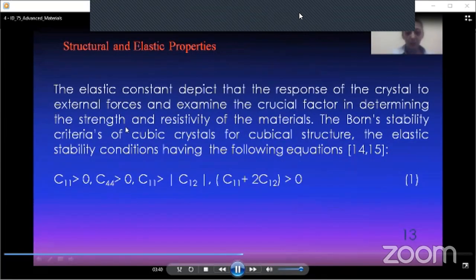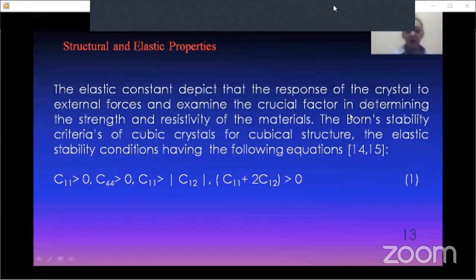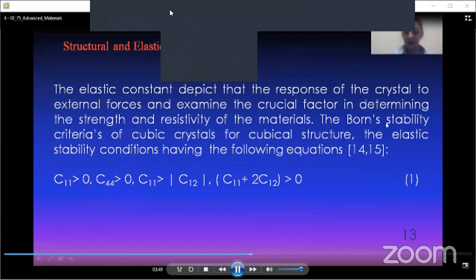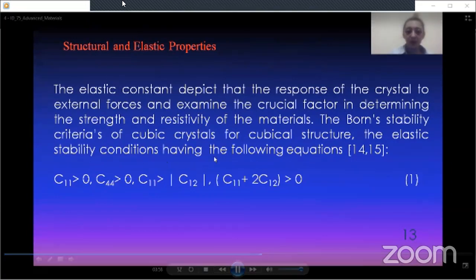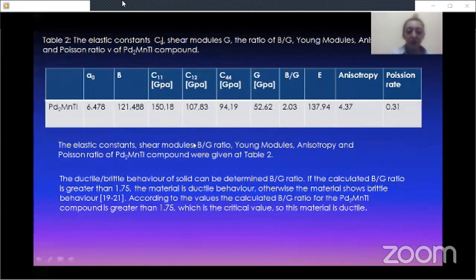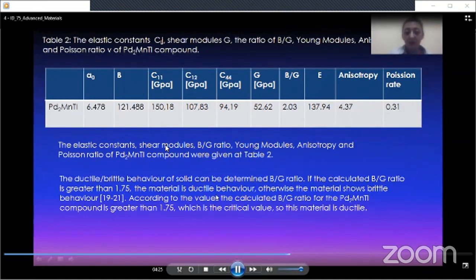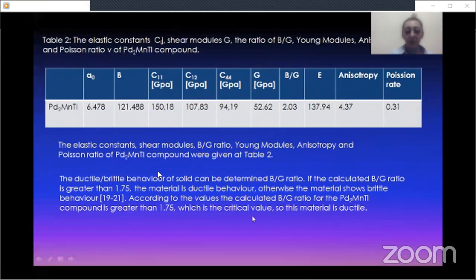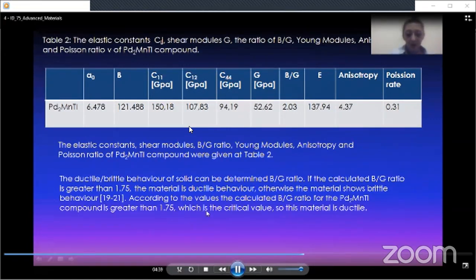The elastic constants depict the response of the crystal to external forces and are a critical factor that determines the strength and resistivity of the materials. For the Born stability criteria of cubic crystals, the elastic stability conditions have the following equations. The elastic constants, shear modulus, B divided by G ratio, Young modulus, anisotropy, and Poisson ratio of these compounds were given in Table 2. The ductile behavior of a solid can be determined by the B divided by G ratio. If the calculated B divided by G ratio is greater than 1.75, the metal shows ductile behavior. Otherwise, the metal shows brittle behavior. According to the values, the calculated B divided by G ratio for this compound is greater than 1.75, which is the critical value, so this material is ductile.